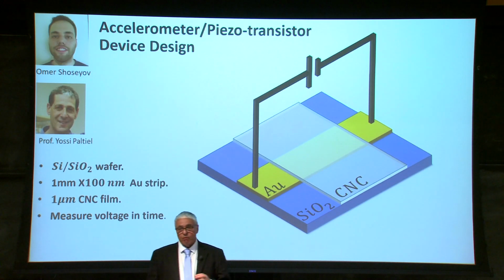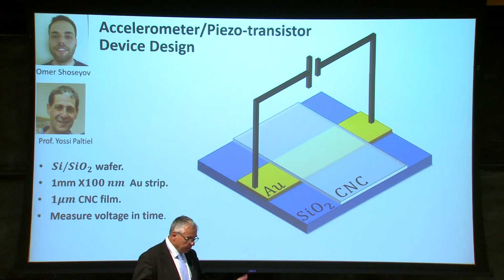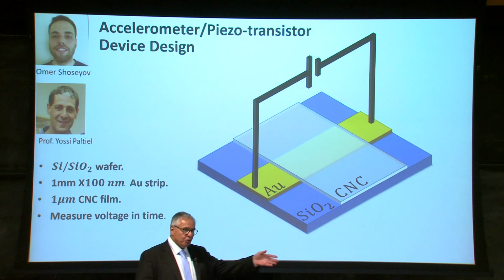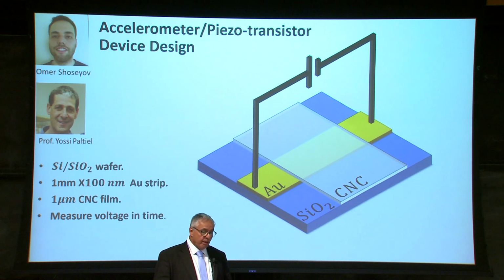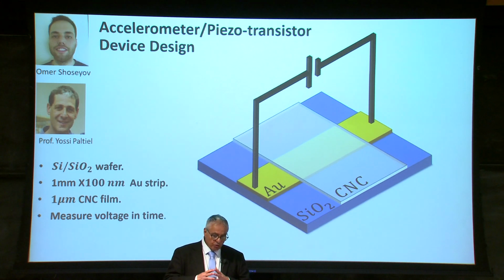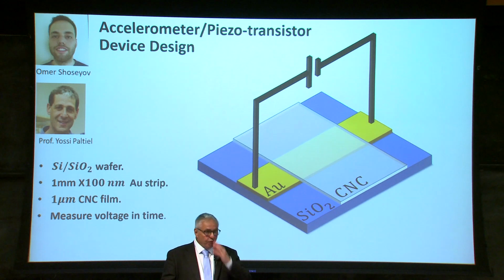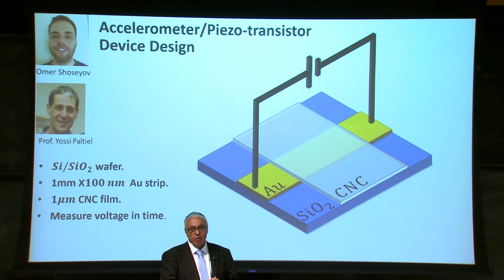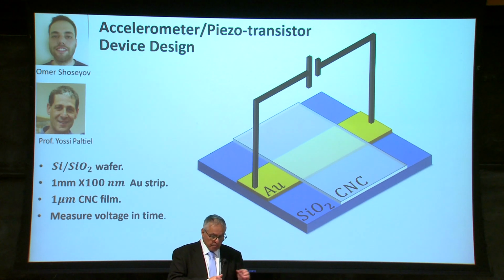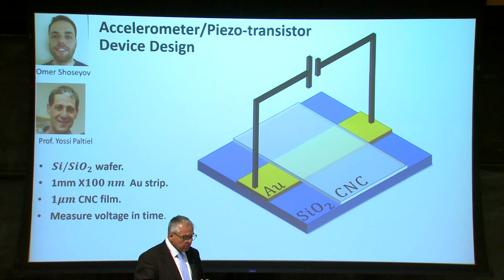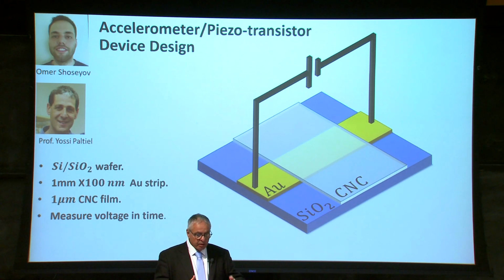Now, in collaboration with Professor Yossi Paltiel from the Applied Physics department, and admittedly with my son, you can see him here, who is a PhD in this group, they developed an accelerometer piezo transistor. The design of that is actually very simple. What they did was apply a very thin layer of gold on a silicon wafer, only 100 nanometers. It's about 1 millimeter thick. And the idea is that once you apply force, it acts like a gating. So it's a piezo transistor, if you like.